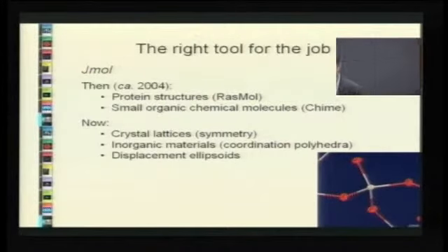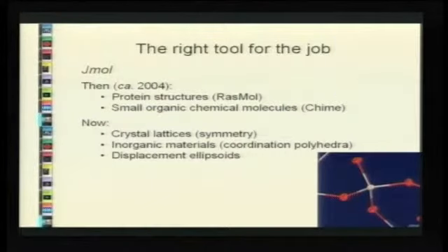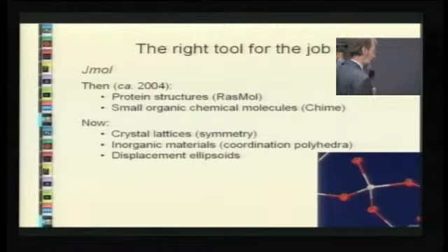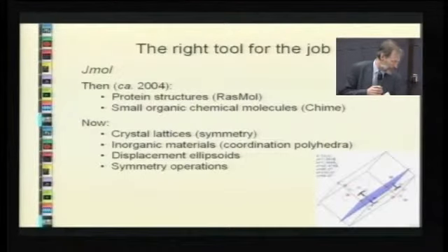In a crystallographic experiment, the result shows not only the position in three-dimensional space of each atom in the structure, but also how mobile it is within the crystal structure, how much each atom can move around its mean position. And these ellipsoids, barely visible, these ellipsoids are visual representations of the amplitude of the oscillations in the three spatial dimensions. So a crystal structure solution is actually a six-dimensional object.